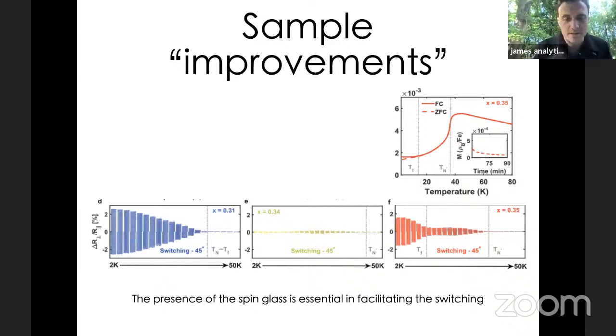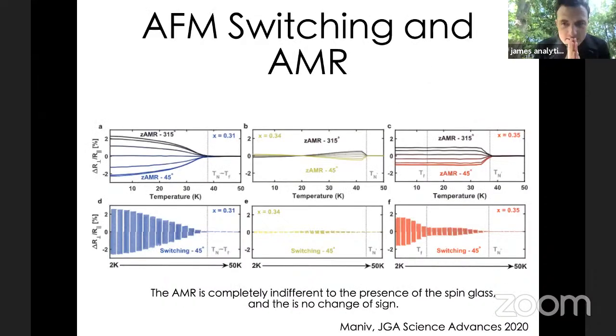But it's not the only thing, as we recently discovered. But let me just summarize that part with this slide. Now, on the top row here, I have the anisotropic magnetoresistance. What I showed you before is a signature of the role of the magnetic order. And what you see in the anisotropic magnetoresistance is no signature of the spin glass whatsoever, and especially in this x equals 0.35 sample, the over-intercalated sample. So the anisotropic magnetoresistance turns on at the Néel temperature just as you would expect it to, and then just saturates. It doesn't care that there's a spin glass turning on around this freezing temperature here, but the switching somehow does. Okay, so why is that?